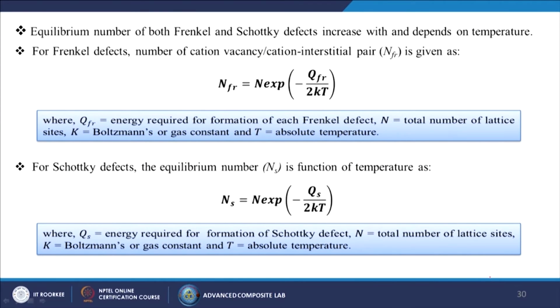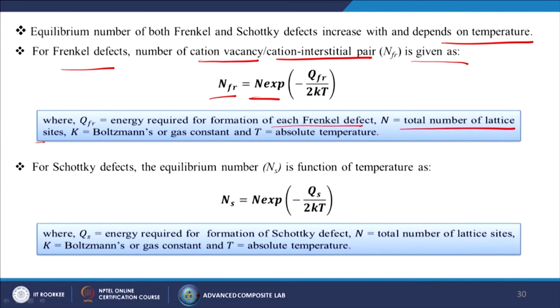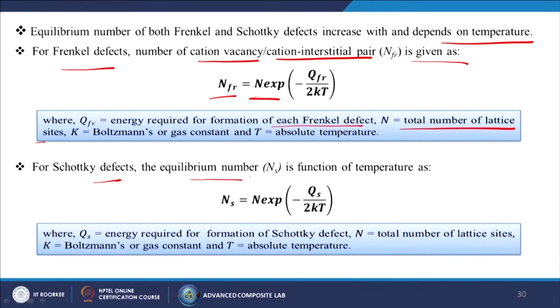So, the equilibrium number of both Frenkel and Schottky defects increases with and depends on the temperature itself. For Frenkel defects, the number of cation vacancy or cation interstitial pairs, which is known as NFR, is given as NFR is equal to N exponential of minus QFR by 2kT. Where QFR is the energy required for formation of each Frenkel defect, N is the total number of lattice sites, k is the Boltzmann constant or maybe the gas constant, and T is the absolute temperature. And for Schottky defects, the equilibrium number Ns is a function of temperature, like Ns is equal to N exponential of minus Qs by 2kT. Here Qs is the energy required for formation of the Schottky defect, N is the total number of lattice sites, k is the Boltzmann constant, and T is the absolute temperature.